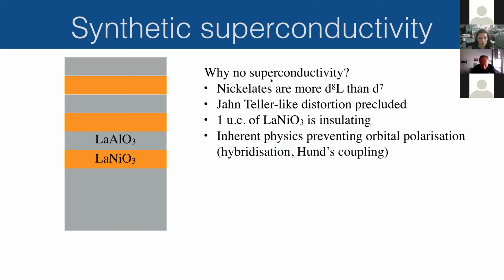So why no superconductivity? Well, the starting configuration of the electronic state is probably not the good one. We have rotations that are coming in instead of Jahn-Teller-like distortions. So the local nickel environment is not really affected by heterostructuring the way that this proposition was assuming it would be. One unit cell of lanthanum nickelate is insulating, so these structures in the end are also insulating.